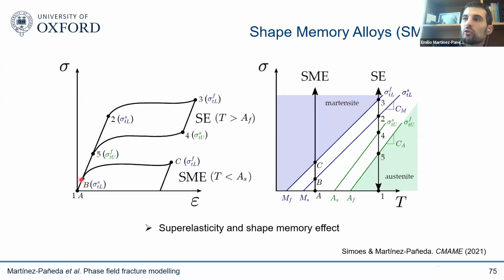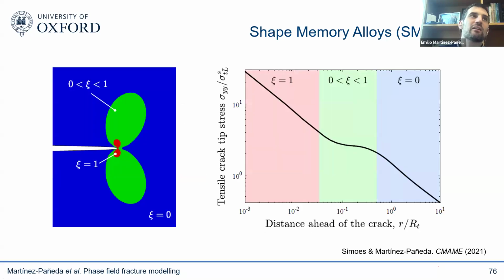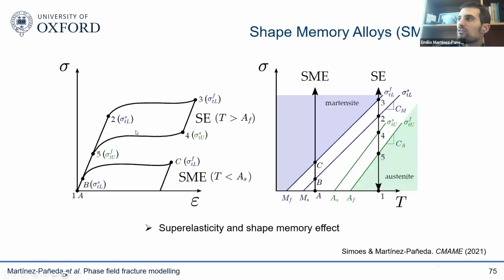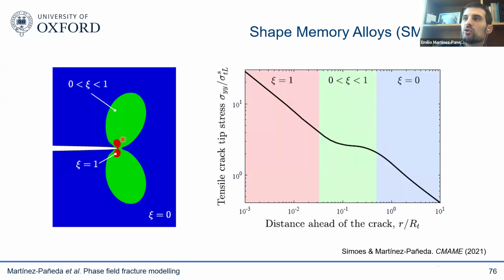You see this here. So you start with the stress strain curve. You start achieving this transformation. So this is 0.2. You start going from austenite to martensite. You get non-linear behavior. But then when you unload, you recover it back again from martensite to austenite, and therefore you go back to your original shape. So you can get very, very large strains that are elastic, not plastic. And then the other effect is this shape memory effect, where you again can recover the original shape by changing the temperature. You go from austenite to martensite and the other way around by playing with temperature. But what this means in fracture mechanics is that because you change phase when you increase your stresses, you're going to have three regions. You're going to have an austenite region far away from the crack. As you start approaching the crack tip and your stresses are large enough, you go from austenite to a transformation zone and eventually to a martensite zone. So you get these three regions.